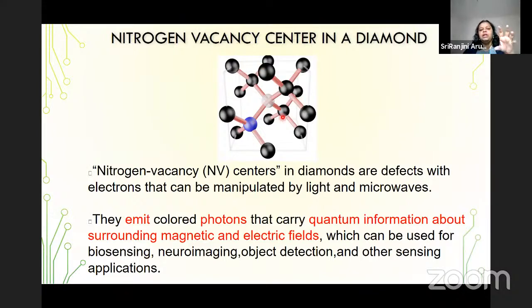Such diamonds, which are made with such a defect process, are called nitrogen vacancy center in diamond. These vacancy centers act as the sensor or the probe for whatever studies we want to do. They can be manipulated both by light and microwaves. And when you shine light on them, they emit colored photons. Basically, the colored photons carry the quantum information about the surrounding magnetic and electric fields.